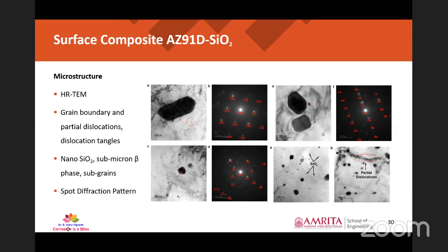So from this we can conclude that friction stir processing has completely disintegrated the beta phase in the matrix, and it has ensured formation of subgrains. So that will lead to improvement in mechanical properties also.